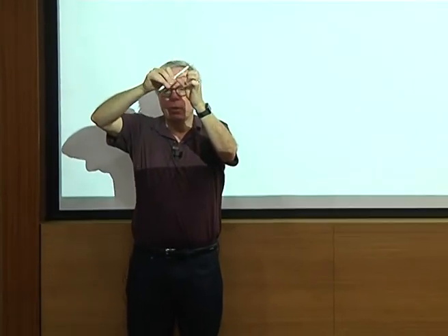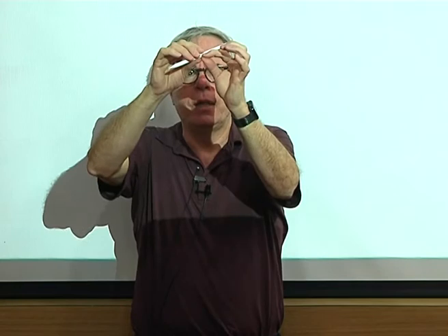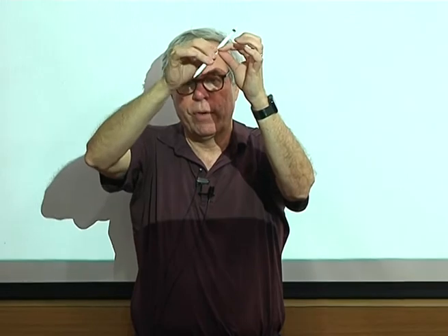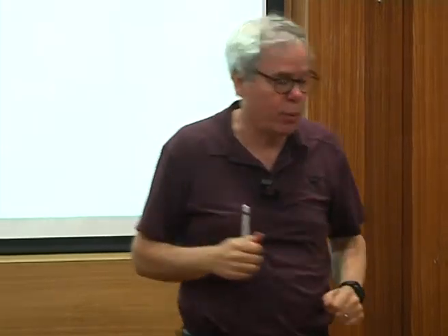Okay? And so what we're going to be talking about here are systems in which these things are viewed as parameters. When you think about composition and the gradients, they're somehow connected, right? So they're smooth profiles. But when we write this energy, what we're thinking about is I give you a composition, and you can actually conceive of doing this, at least in your mind, where you fix the composition, and I say, okay, what is the gradient? And what it's saying is that the energy is going to change depending upon what that gradient is. And so you want to view these gradients here as parameters in the free energy. They're things that you can vary independently from the actual value of the composition at that point.